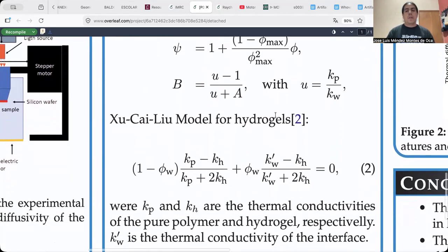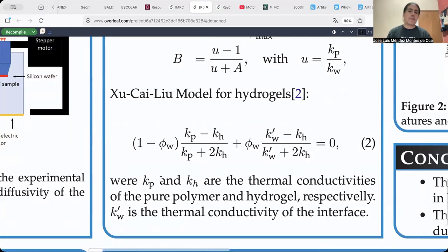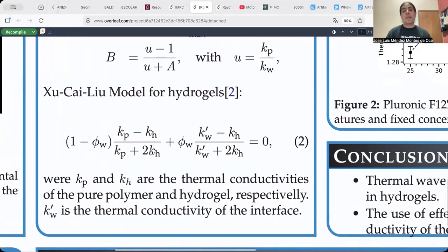And this is another model that we used, the Xu-Cai-Liu model for hydrogels, which is quite different. It takes into account the hydrogel as a sphere filled with water and with an interface in between. Here we have Kp as the thermal conductivity of the pure polymer, Kh as the thermal conductivity of the hydrogel, and Kw prime as the thermal conductivity of the interface. And this is the main equation of that model.